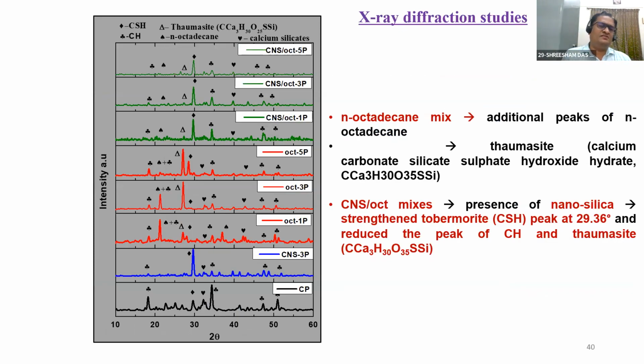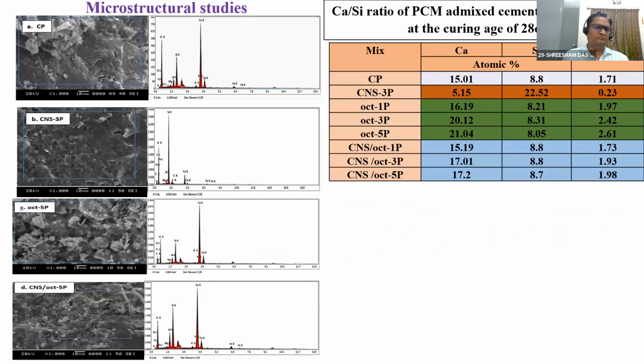Well, this is your X-ray diffraction. What it gives me, you can see, is that the colloidal nanosilica plus octadecane mix is giving me strengthened tobermorite and a reduced peak of calcium hydroxide. If you see only the n-octadecane mix, we have a sufficient amount of calcium hydroxide. That is the difference. All other things are almost similar here.